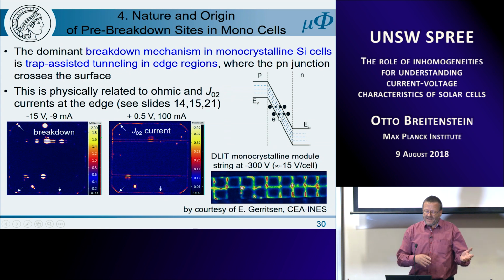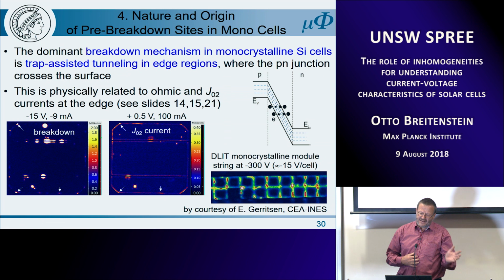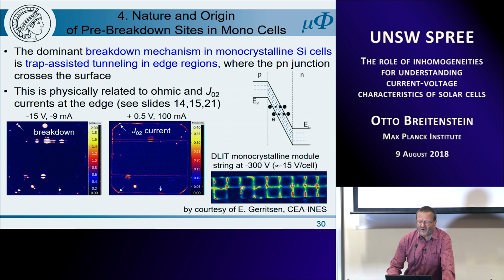So we already in the IV characteristics I have shown before had some positive slope, some super linear behavior which pointed to field dependence, and I believe that this current is trap-assisted tunneling in the edge region, but multi-trap assisted tunneling.